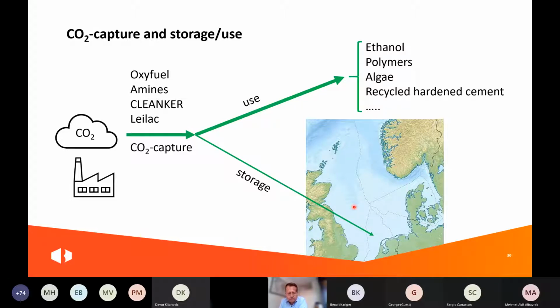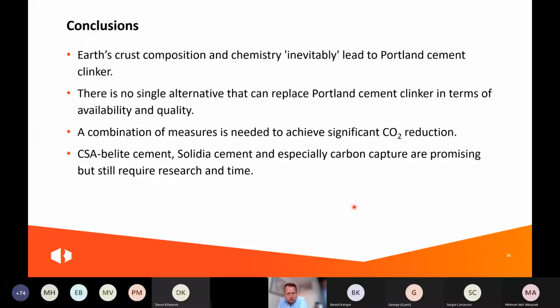If you use the smart crusher, you will end up with cement stone, and if you grind it and activate it with CO2, you will have a product you can use again as a main component in cement. So conclusions, if you look at the earth crust composition and chemistry, then it leads to Portland cement. So it was not by chance that we ended up with Portland cement, and there is no alternative that can replace Portland cement clinker in terms of availability and quality.